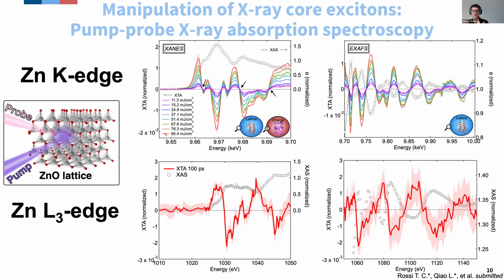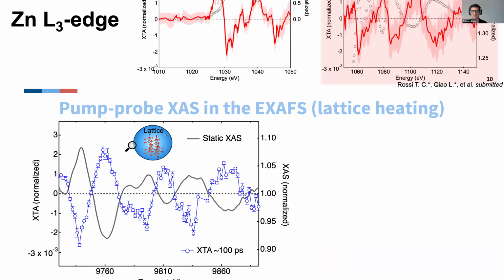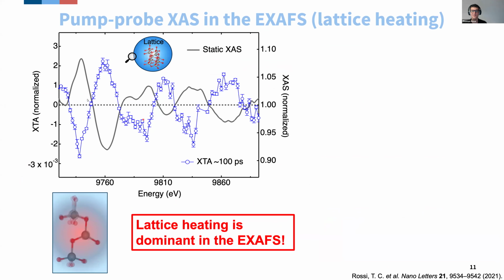And the strategy to interpret these spectra is always starting from the EXAFS. The reason for that is this unique sensitivity to the structure that I described before. It would be way more complicated to look at the XANES first because it is sensitive to two different degrees of freedom. So I will focus on the zinc edge and try to convince you that it's actually pretty simple to understand what's happening in the EXAFS.